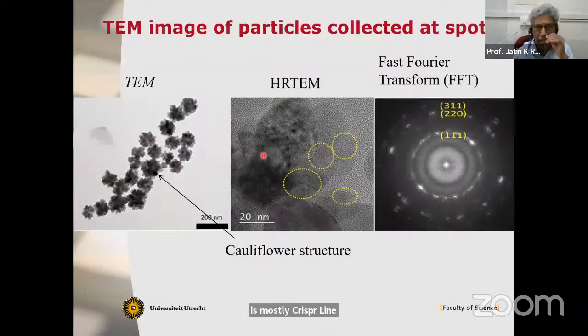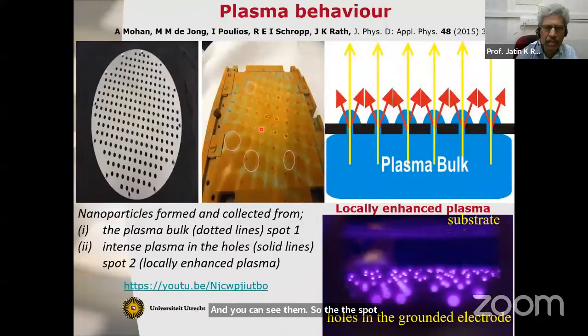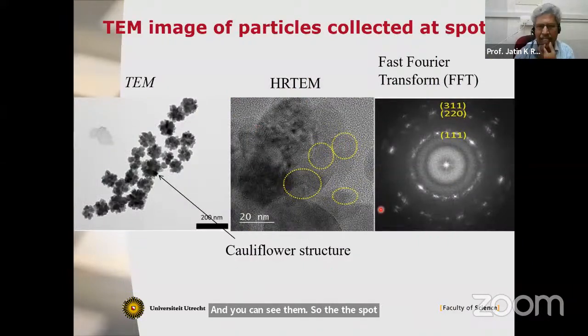And you can see them. So the spot one, that is this spot, the small ones, they are basically crystalline. You can see them also from the TEM picture and the fast Fourier transform of them. You can see them; they're all crystalline.